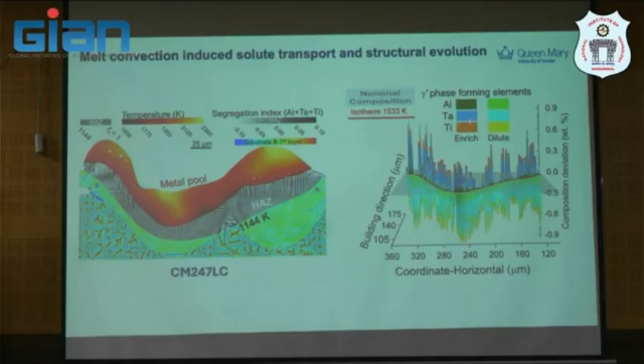There is preferential segregation of some element based on the calculation here, that in the isotherm of the solidus temperature of this melt pool, you will see that there will be some in the liquid and in the solid. That's what we call dilute or enrich. It's based on quantitative measurement here. So previous slide, that's what we do. So we will see that in the liquid, this actually dilute or otherwise enriched zone.